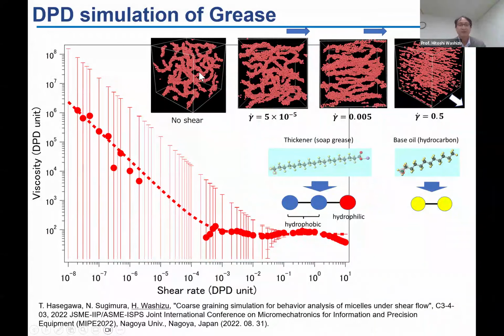And here's a no-shear structure. They make a self-organization structure, and then if we add some shear, we can get this kind of structure, and then under high shear, the micelles break down, and then we can obtain the viscosity. The viscosity curve decreases in the first regime. The first regime is a rotation of the micelles, the fibers of the micelles, and then it becomes like this, and then gets some plateau value, and then at much higher shear, the structure of the micelles breaks down.